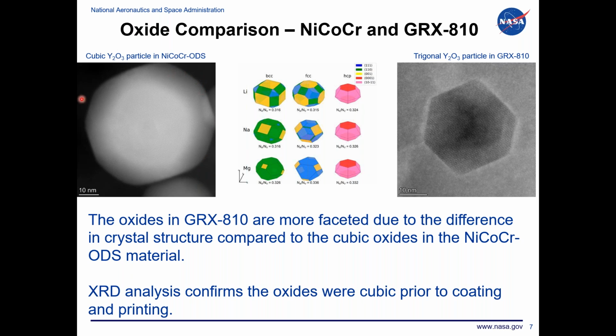Now, what's interesting is that for GRX 810, the yttria is no longer cubic. It's a trigonal crystal structure, which is a very unique crystal structure, and one, according to literature, that just is not stable at room temperature or even at elevated temperatures. It's really only stable under very high pressures, I think 12 gigapascals. And past studies, as soon as we release that pressure, it reverts back to a different crystal structure. And so there's very little research on this specific crystal structure, but for some reason, we're forming trigonal yttria oxides in GRX 810.